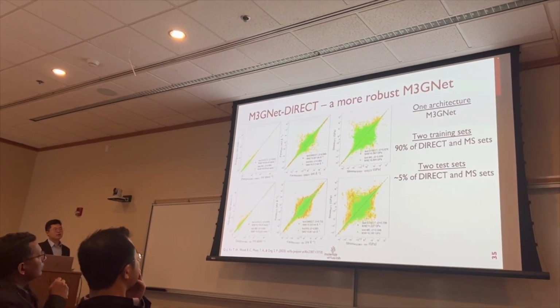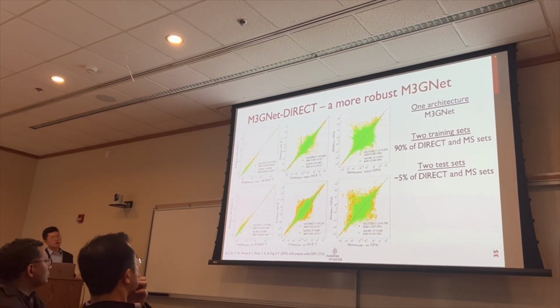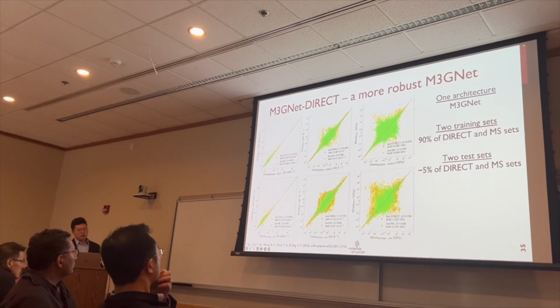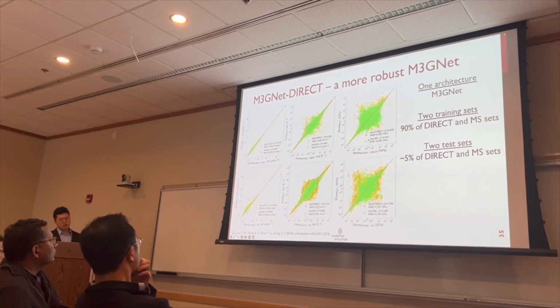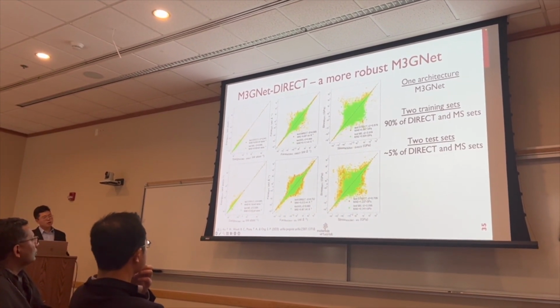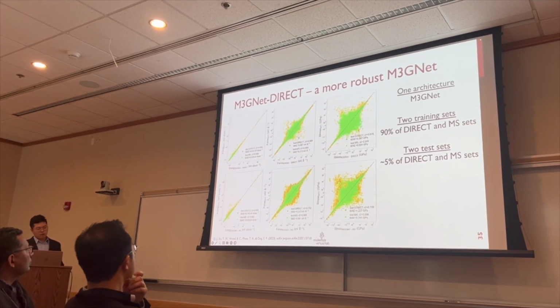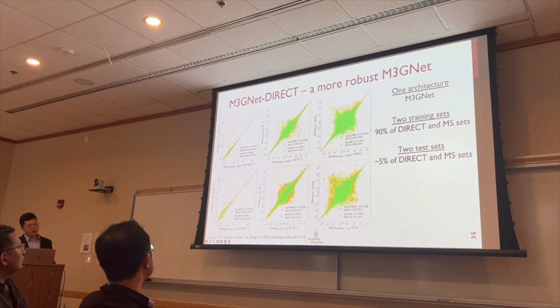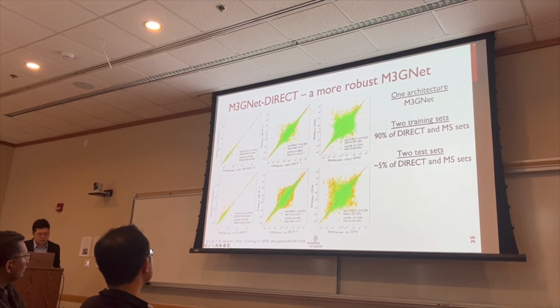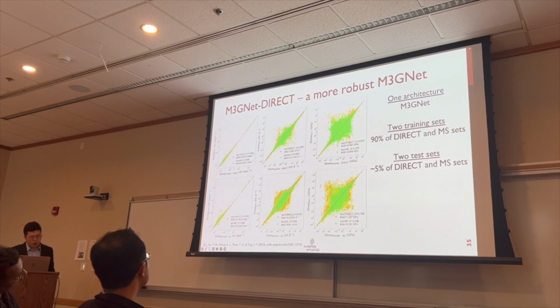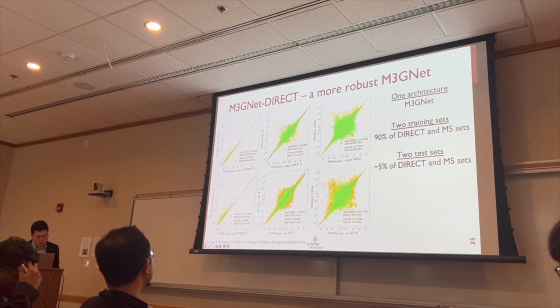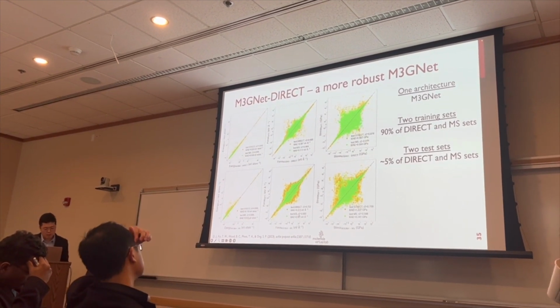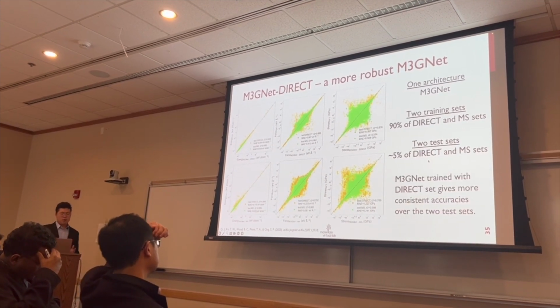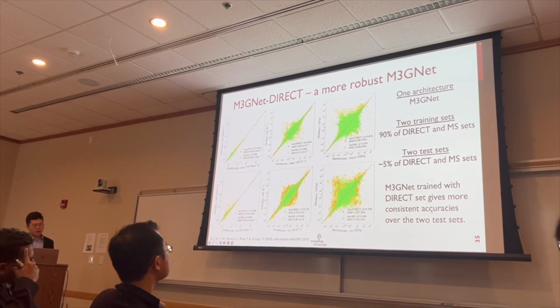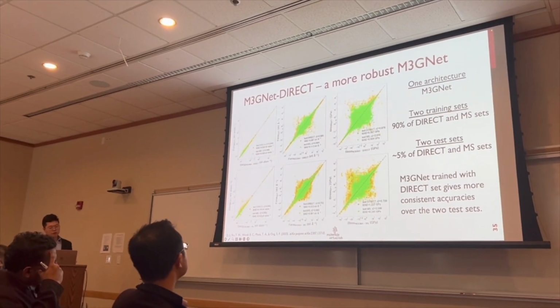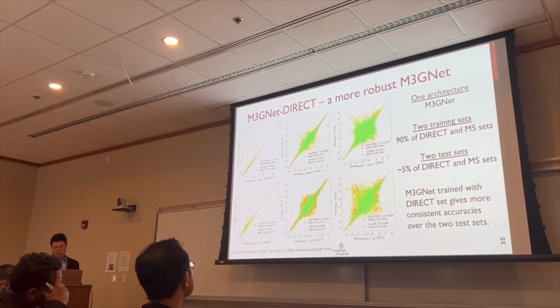And then we use this direct dataset to train M3GNet models and compare the result with the manual sample dataset. So the above are the parity plots for energy, force, and stress calculations by the M3GNet trained with the direct dataset, and below is by the manual sample dataset. We can see, for example, for force, the M3GNet direct has a test error around 0.1 eV per angstrom for both the test sets, while the manual sample model has a much larger error for the direct test set, while much lower error for the manual sample test set. This tells us that the M3GNet training with direct set gives a more consistent accuracy over the two test sets, especially for those more challenging cases.